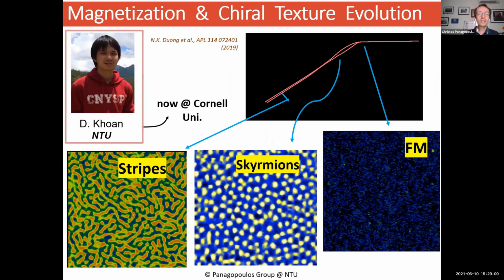So Khoan, who graduated last year, was able to find a very beautiful way of characterizing skyrmions from bulk magnetization. So here on the right-hand side, what Khoan was able to show many times is that there is a tiny region of magnetization as a function of magnetic field where you observe a little hysteresis. And in this hysteresis is where you have this beautiful skyrmion formation that I discussed before. At higher fields, it saturates to a ferromagnet. At lower fields, you have magnetic stripes.